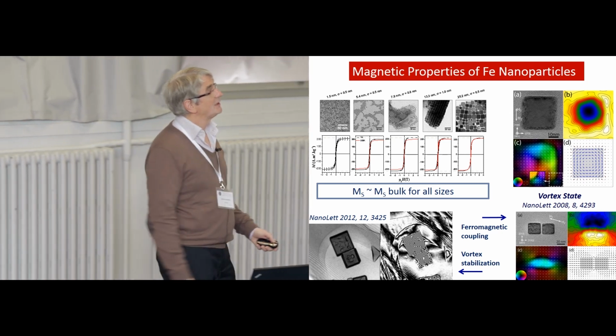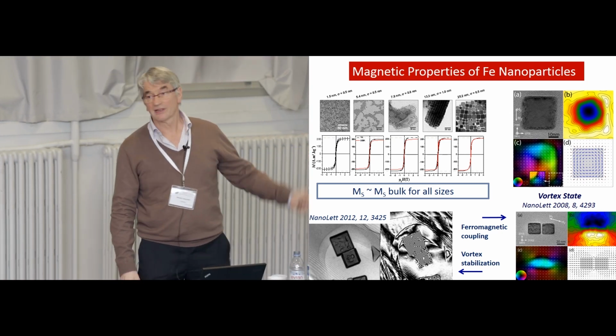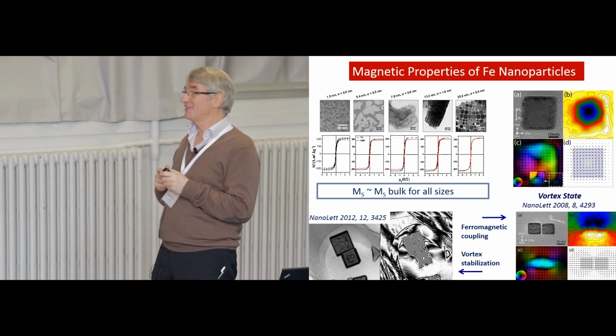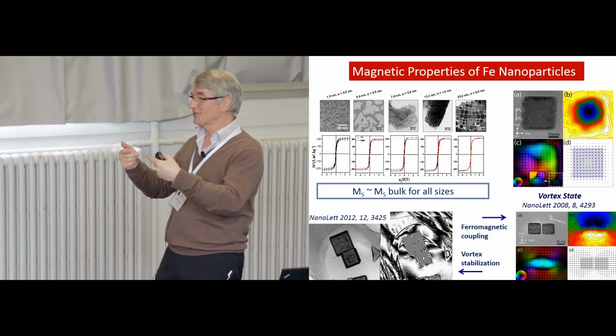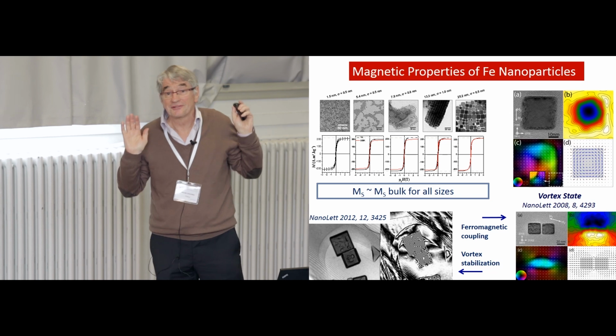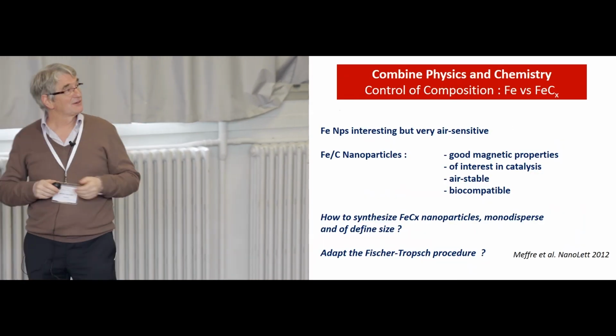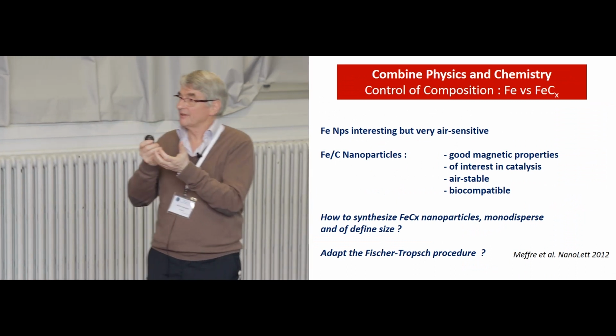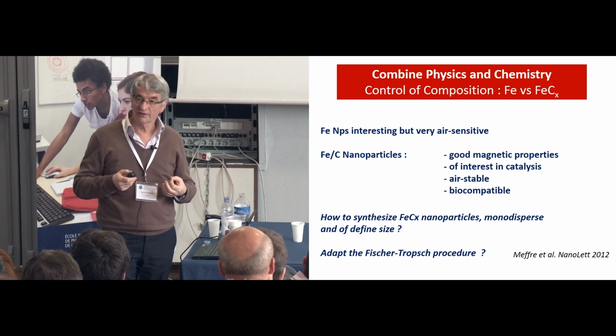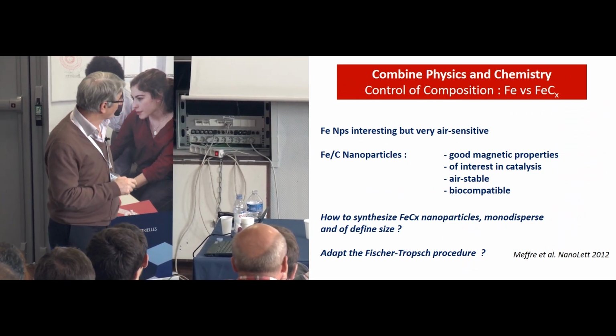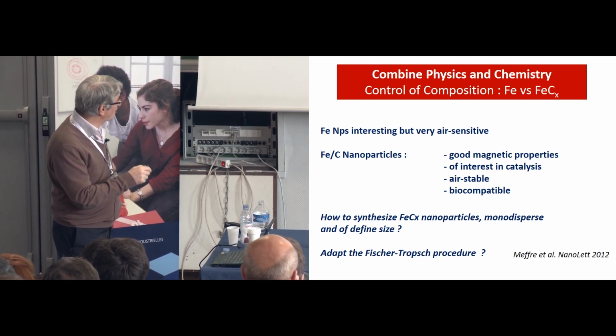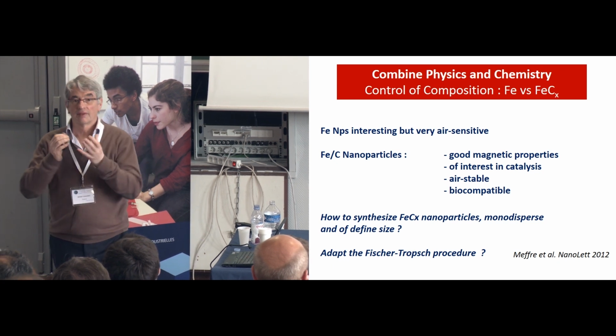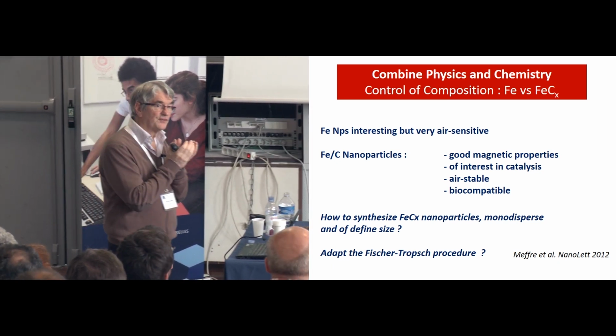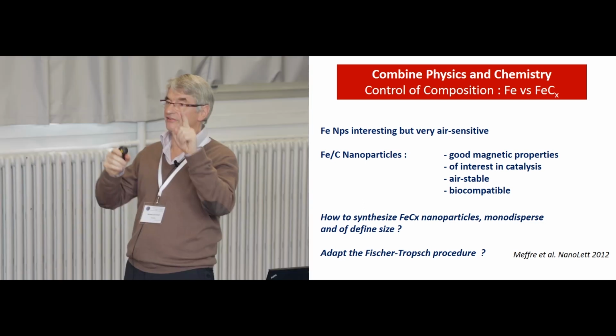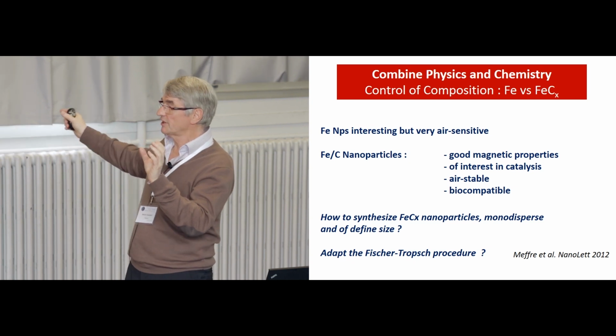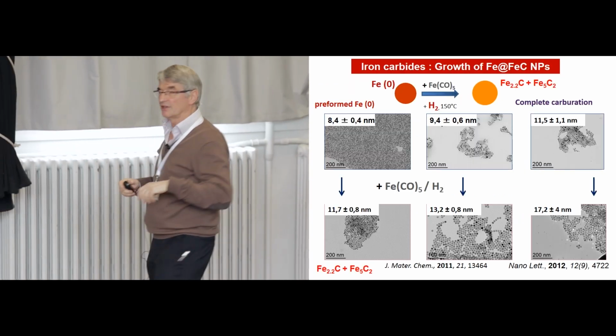To finish, yes, the iron nanoparticles are interesting, but some of them burn in air. And when you give that to physicists to measure transport properties, some physicists don't like it, I don't know why, but... So the idea is, can we make something which is like iron but doesn't burn in air? And there is iron carbide. So we took monodispersed nanoparticles of iron, and to make carbide, we were inspired by the Fischer-Tropsch process - carbon monoxide plus hydrogen, which gives gasoline. It was used by the Germans during the Second World War.